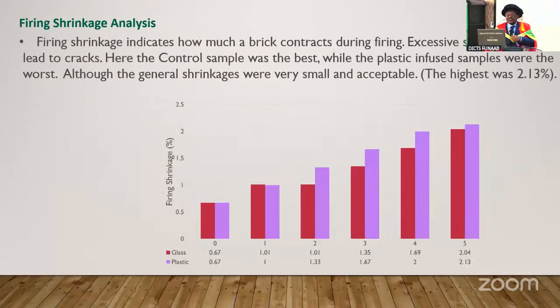Firing shrinkage indicates how much a brick contracts during firing. Excessive shrinkage can lead to cracks. Here, the control sample was the best, while the plastic infused samples were the worst. Although the general shrinkage was very small and acceptable, the highest was 2.13%, which is also acceptable, by the way.